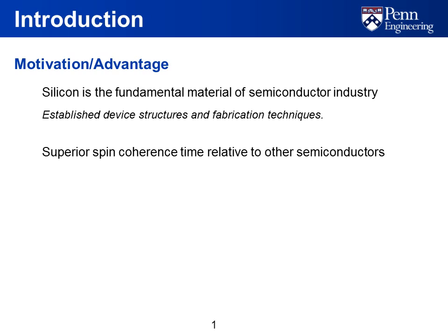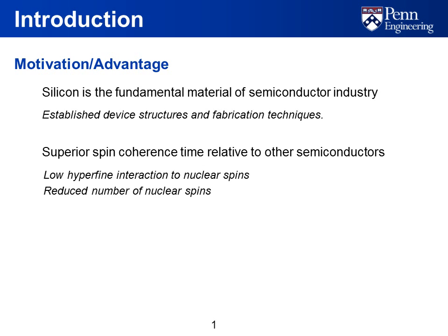Secondly, it has superior spin coherence time relative to other semiconductors, which is due to the low hyperfine interaction with nuclear spins and the reduced number of nuclear spins.